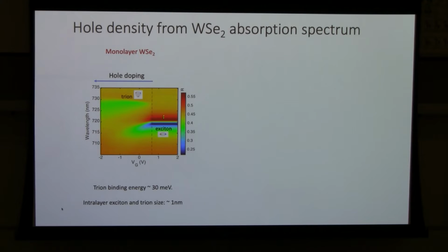If you do a vertical cut, you can see there's a very strong resonance here. And this resonance corresponds to the creation of bound excitons. Then when you go along this direction, holes start to dope into the system. So this corresponds to increased hole doping. And when you have increased hole doping, you can see that this exciton resonance gets shifted and also reduced. But at the same time, a new resonance comes out.